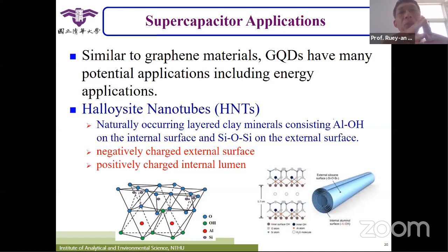And here we select a naturally occurring material as the support. We call this one halloysite nanotube. Halloysite nanotubes are a naturally occurring layered clay mineral. We can find these materials in soil. The characteristic of this material is that it contains aluminum oxide on the inner surface, and silicon dioxide on the outer part. And from soil chemistry, you will know that the layers need to balance. Alumina is 3+, silicon is 4+. So when they are in the same material, most of the time your silicons will become negatively charged, and your aluminums will become positively charged. So this material has been widely used to absorb metal ions in soil.